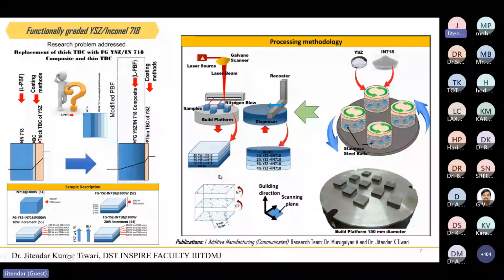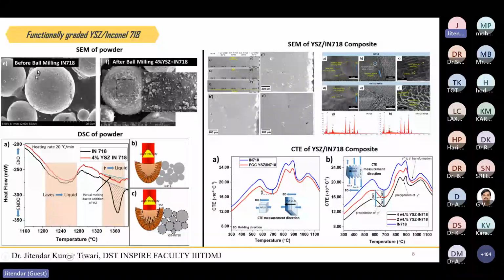Before that, I would like to share some results about this particular material. Here you can see this is Inconel 718 gas atomized powder, after coating with yttria stabilized zirconia; basically during ball milling the yttria stabilized zirconia got coated on the surface of the powder. The thing is, it's again not very straightforward that you can just mix the powder and easily print the functionally graded material. It needs lots of investigation. We are also working in that direction. Let's say if you are changing your composition in LPBF, you have to change the parameters.